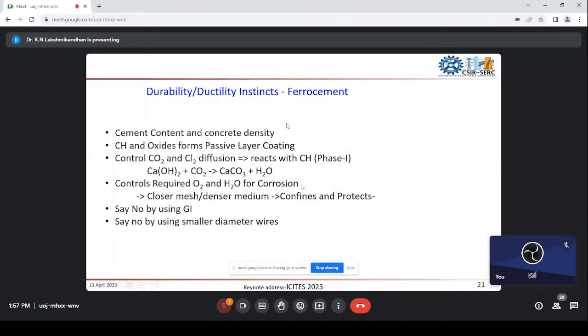From the basics of material characterization, what we found is cement content. If you have more cement content, there will be more calcium hydroxide. And if the concrete is very dense, then it will not permit any water or oxygen to enter. So this way we can control it. One is keeping the passive layer sufficient, and second is keeping the density very high, so that we are protecting the concrete composite.